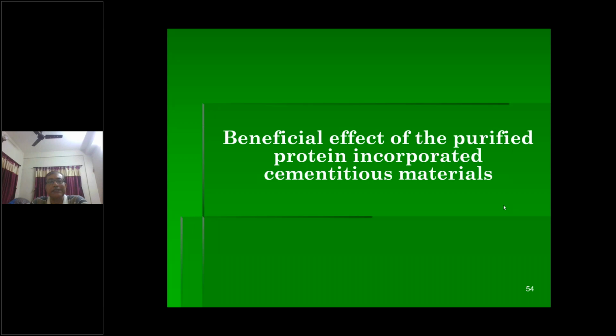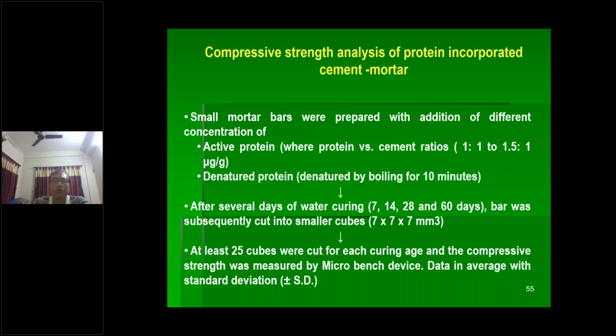So now we have studied the beneficial effect of this purified protein when it is incorporated in cementitious material. As the quantity is very small, small mortar bars have been prepared with the addition of different concentrations. Only the protein and the cement are used in these cases. The ratio of protein to cement is given in microgram per gram, that is, 1 microgram of protein added to 1 gram of cement. We have also used denatured protein, boiled for 10 minutes, as I have already discussed.